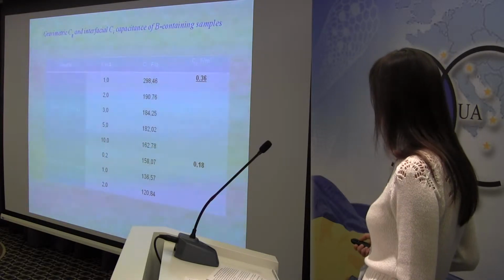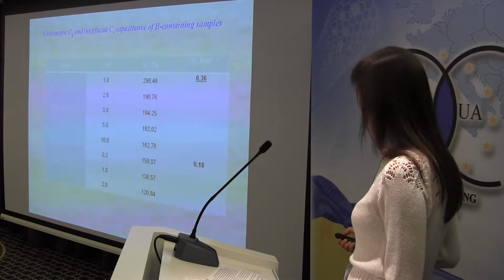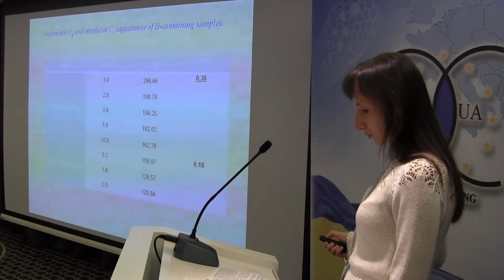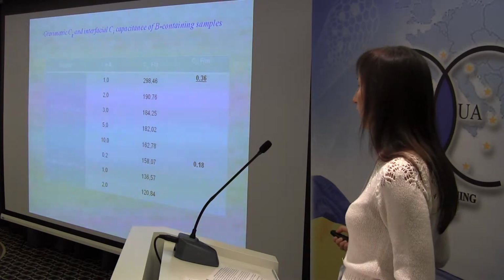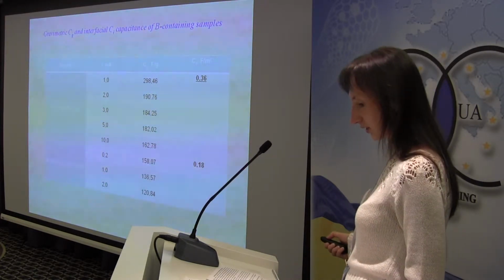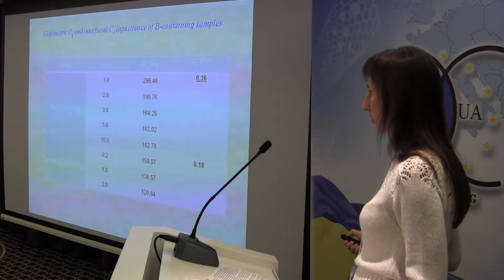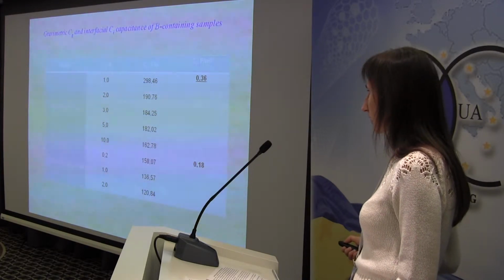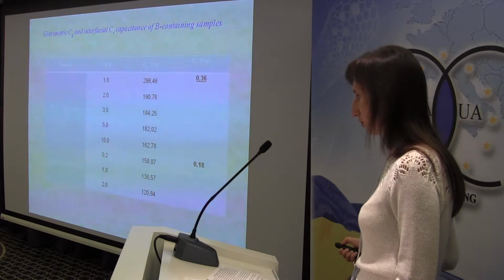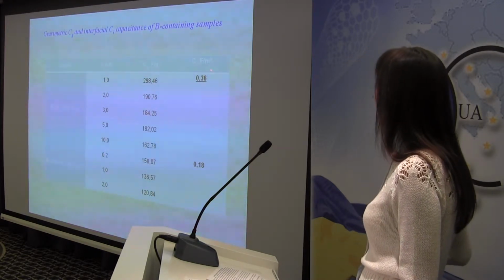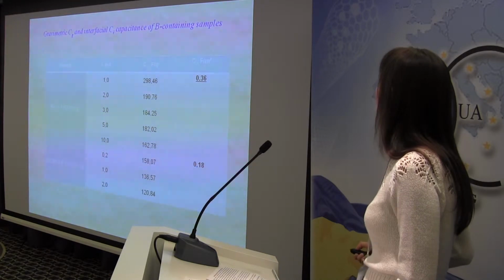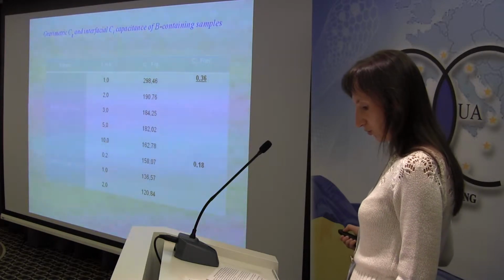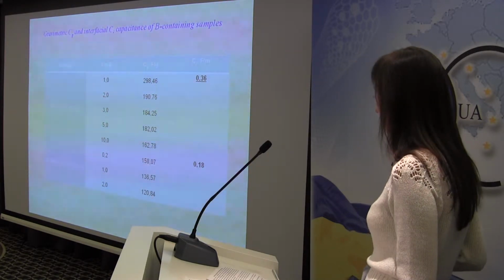The obtained boron-containing materials show large gravimetric and interfacial capacitance, in contrast to carbon without boron, which is not electrochemically active. This is stipulated by incorporation of boron into the carbon framework and formation of surface chemical structures. Boron-containing carbon samples exhibit superior interfacial capacity, 0.18 or 0.26 farad per square meter for meso and microporous carbon respectively.